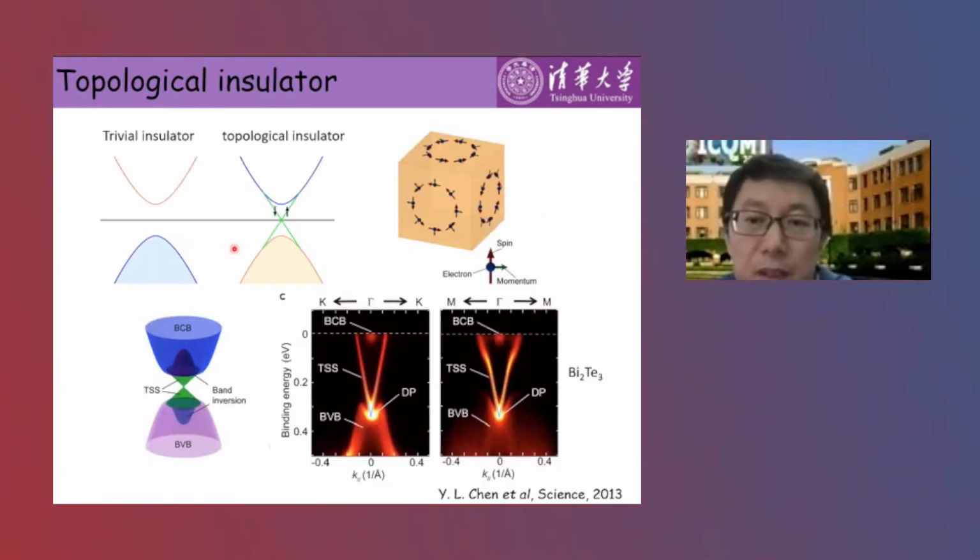The major difference between the topological insulator and the normal insulator is the inverted band gap and the existence of the topological surface states. In the topological insulator, the strong spin orbit coupling plays a role as the external magnetic field in the quantum Hall state. The spin and the momentum of the surface states are locked, forming a gapless Dirac cone in the bulk gap. Due to this spin momentum locking, the electrons are immune to the backscattering induced by non-magnetic impurities. Therefore, the topological insulator is potentially useful for low energy consumption electronic devices.